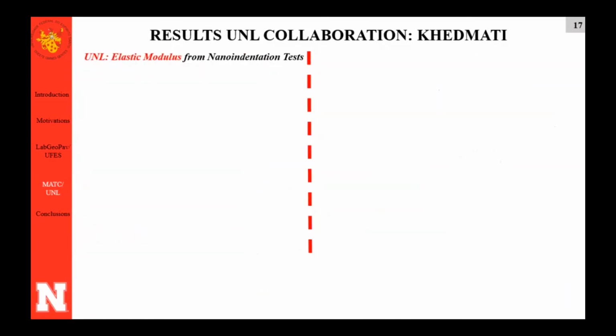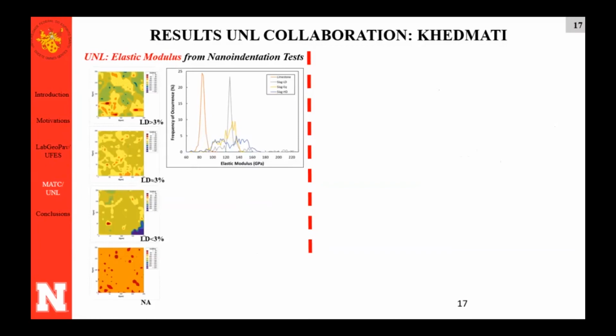So from the nano-indentation results, what I could think, and again, it's still thinking, it's a never-ending process, but my initial thought was, from the nano-indentation test, we can see this is natural aggregate and seems pretty homogeneous when you look using the nano-indentation equipment. This was expected, as Madia told me, for natural aggregates, pretty homogeneous, but she was surprised when we put the first sample of slag and we saw heterogeneities throughout the analyzed area. And this heterogeneity seems to decrease as the slag is cured, at least from this parameter point of view, from the elastic modulus.